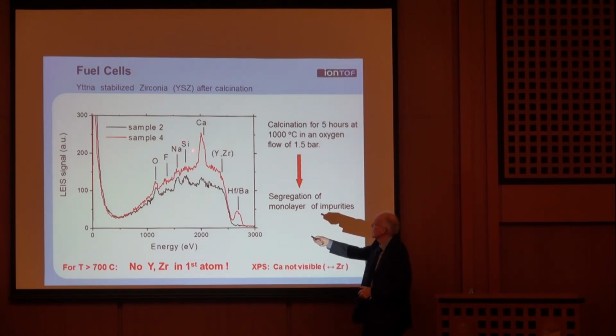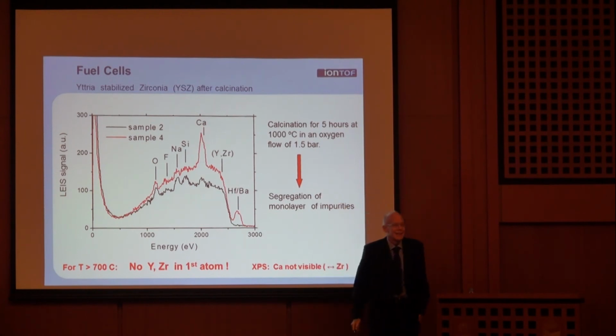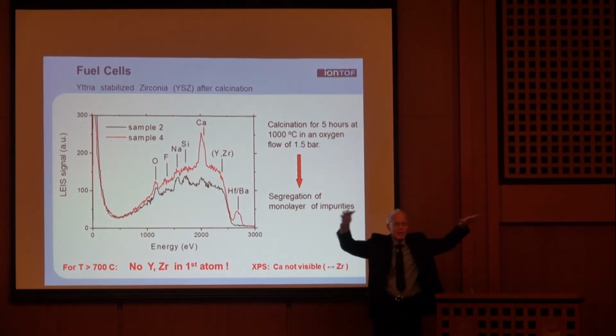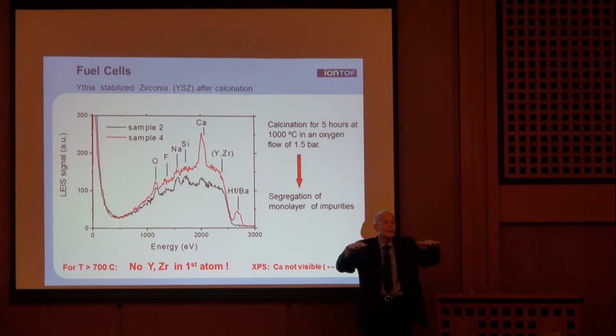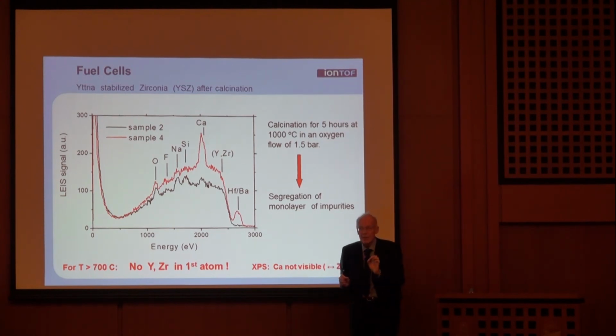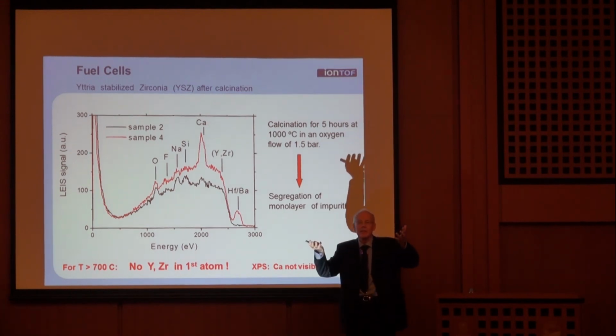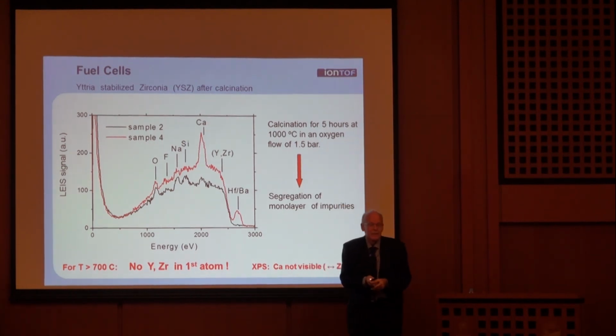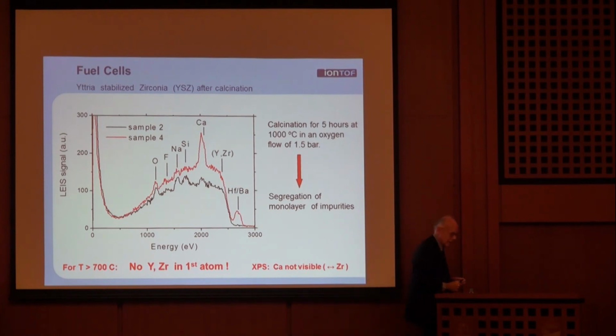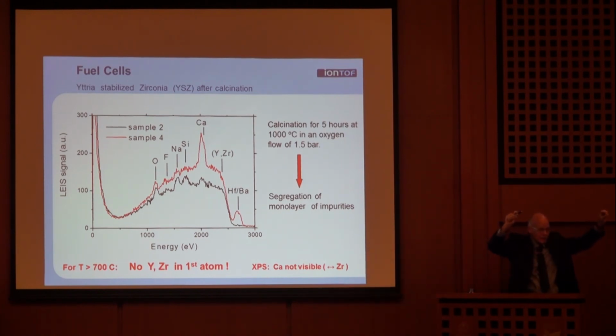Fluorine, sodium, silicon, calcium, hafnium, all kinds of things at the surface, but no yttria and zirconia. That is because once you activate this and go to the temperatures where the SOFC should work, impurities come from below and segregate to the surface. They kill the surface. It's only the top layer. The second layer is yttria and zirconia.